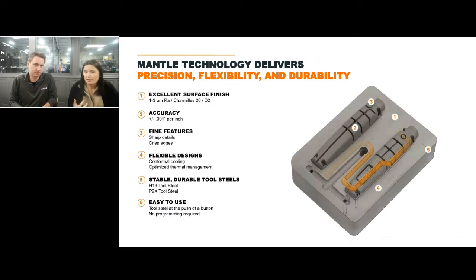shop floor. So we met Mantle in 2019, and we were quickly impressed with the product samples they gave us. We did a basic machining test, something similar to this that you can see in front of you. We put it through grind, wire EDM, sinker EDM, and machining, and we were extremely impressed with both the surface finish and the accuracy. Mantle comes off the printer and sintering at plus or minus 1 thou per inch, and a lot of times we're seeing that or better.